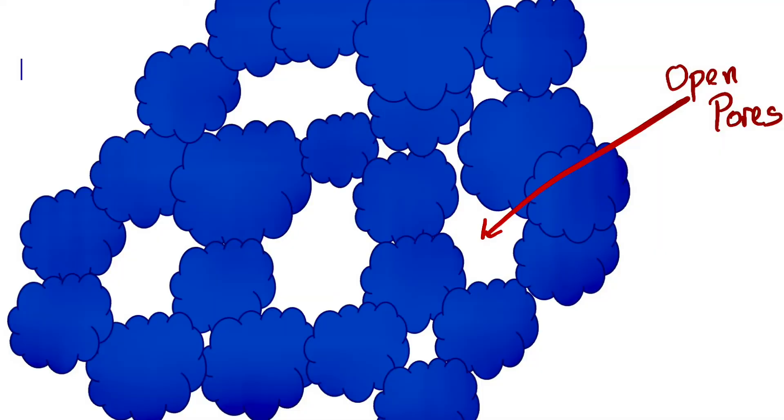The key difference between these three plates and their ceramics is what's known as their open porosity — the amount of space that actually exists within the plate itself. If you imagine that the clay is made up of lots of particles, and when you fire the plate these particles are glued together. Now with the earthenware plate, it's fired at a very low temperature, about 950 degrees centigrade, and these particles, although they glue together, leave lots of little gaps between them. This is known as open porosity, and this open porosity allows the ceramic to act as a sponge and soak things up, like the water that it was soaked in before the test.